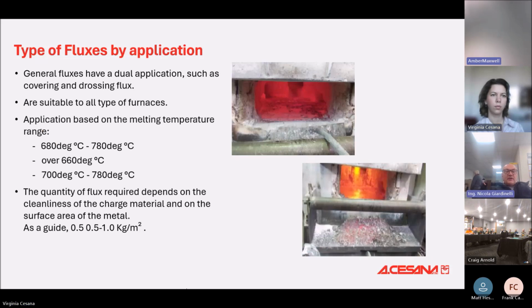So the typical flux has a dual application, such as covering and drossing flux. At the same time, we have a flux that can protect the bath of the aluminium and also has a drossing effect on the aluminium. This flux is suitable for all furnaces: melting furnace, holding furnace, electrical or gas furnace. It's not a problem. And the application starts from 680 up to 780 degrees.